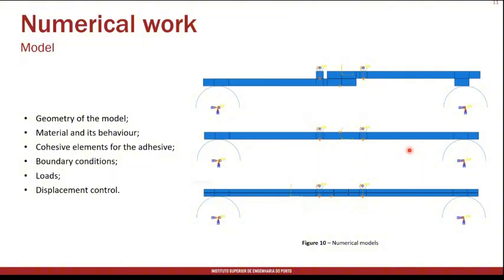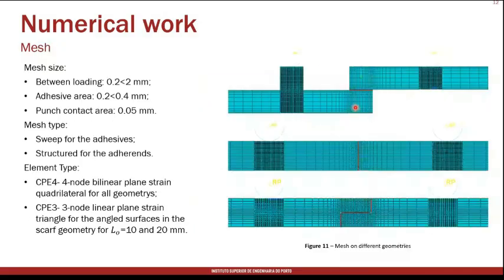Numerically, we modeled the geometries in Abaqus, and we used cohesive elements with a triangular mixed mode law, so that we can simulate damage initiation and propagation in the adhesive layer. And here we can see the setup for each type of the 3 joints. We have a 4-point bending setup with 2 supporting rollers, 2 loading cylinders, and the part of the joint where we will have failure either by plasticity of the adherent or by cohesive fracture of the adhesive layer.